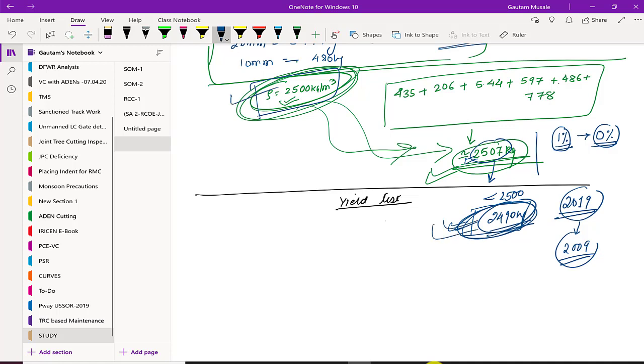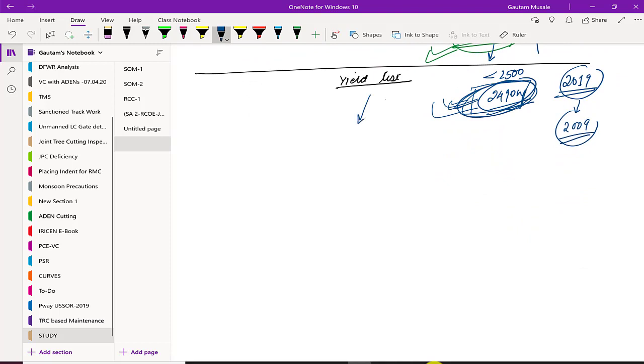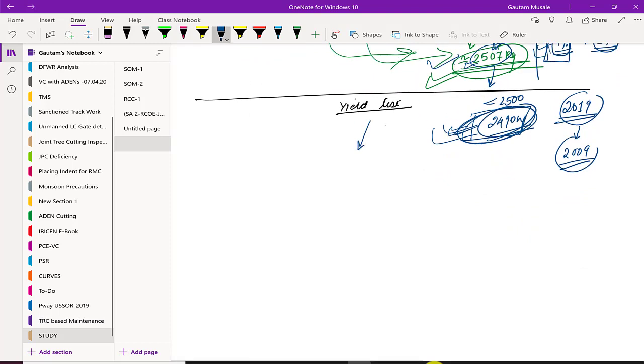I even confirmed it with the yield test also. It also showed me that it is lesser than 2500, and that is how I came to know the importance of incorporating 1% air entrainment. After I included 1% air entrainment, I observed the density of 2507 by the thumb rule, as well as when I performed the yield test, my density lay nearby 2507, definitely more than 2500 kgs. So that clearly reflected the importance of incorporating the 1% air entrainment in the volume of the concrete.